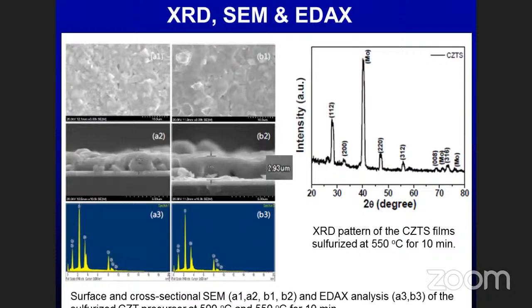Yeah, this is the XRD patterns. See, this one is the XRD patterns. We use the moly substrate. That's why the high intensity is related to the moly, and this 112 is a peak. This belongs to the kesterite phase of the CZTS, and that sample was sulfurized at 550 for 10 minutes. Okay, and see there is the surface morphology of this one and the cross-section morphology of the CZTS device having a thickness of 2.9 micrometer.